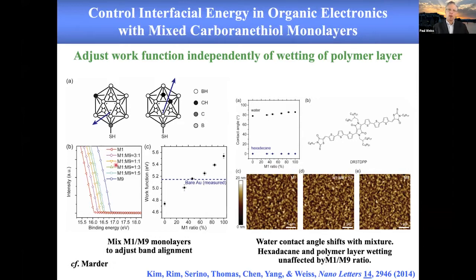And so Jay hypothesized that if we took two different carboranes and we mixed them on the surface, that we could then vary the surface charge essentially continuously, and we could get perfect band alignment in that way. And he did that using these two molecules. He was able to tune the surface potential over 1 electron volt, which is plenty, on both gold and silver surfaces. He was able to show that he didn't change the wetting properties and he didn't change the morphology of the active layer on top there.